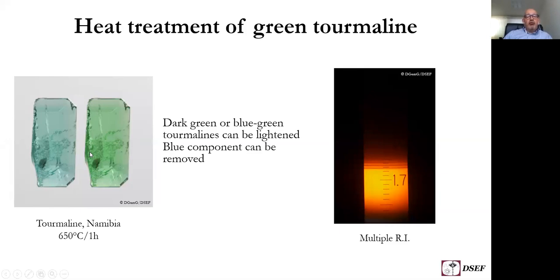Now, commonly tourmalines, those which are in the trade, when they are of good quality, are pretty clean. So unlike in corundum, there are not that many inclusions from which you might conclude that the stone is heat treated. Well, very often you cannot tell. In green tourmalines, sometimes if you put them on the refractometer, you can see these multiple refractive indices, as you can see here. And this is actually due to the fact that during the heat treatment, there will be produced some so-called vicinal phases, very small, submicroscopically small phases, which actually produce these multiple readings. So if you see tourmaline with these multiple readings, you can be pretty sure that the stone is heat treated.